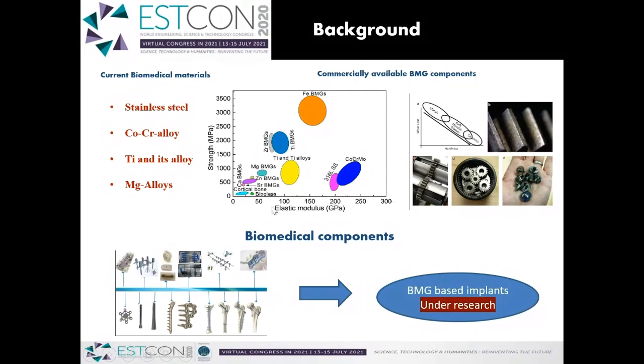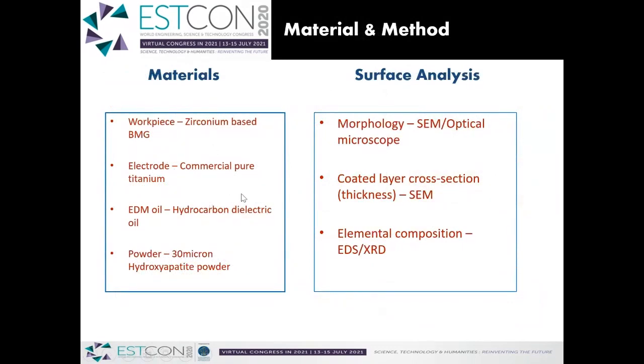So we proposed this material due to its unique properties. BMG is also a newcomer in the field of biomedical, although BMG has been utilized to produce numerous components for automobiles, aerospace, and other applications. The materials we used, as previously stated, are a zirconium-based BMG, and commercial pure titanium as electrode, and we used a hydrocarbon-based dielectric fluid. And we used hydroxyapatite powder, because of its biocompatibility, to be added into the dielectric fluid. Various characterization techniques will be employed to assess the experimental results.